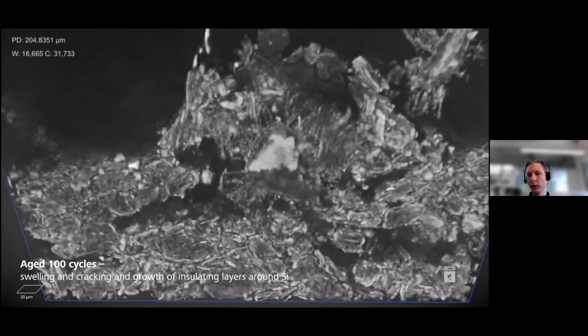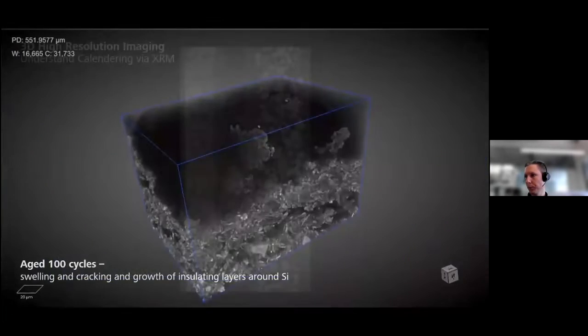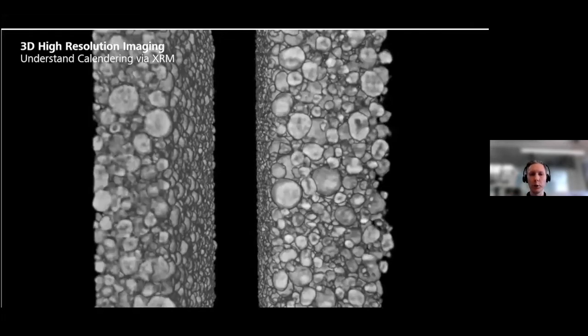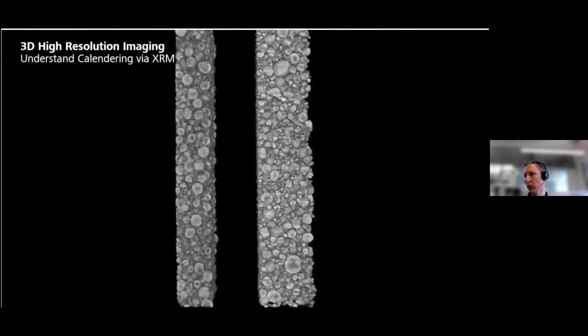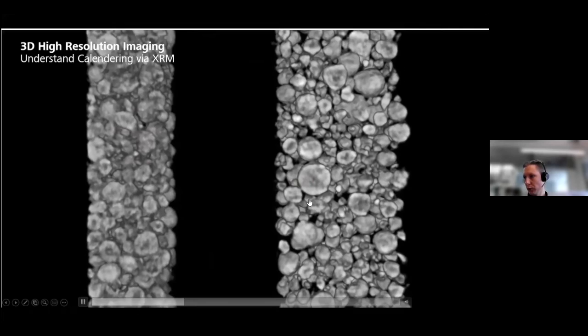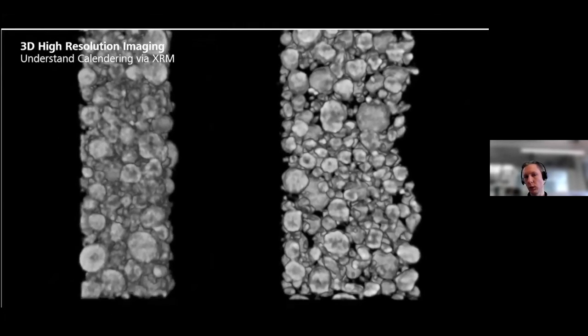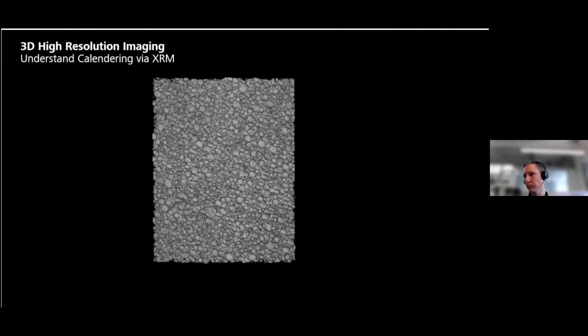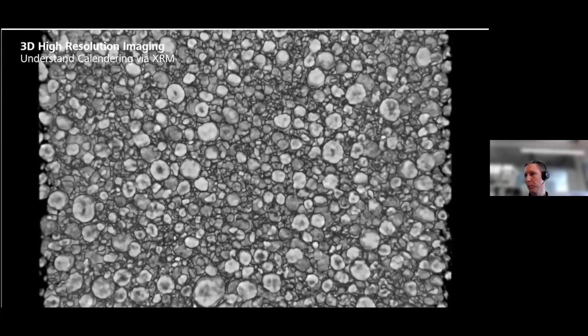You cannot only take a detailed look at the materials, but also use the X-ray microscope for optimizing your process parameters. Here we can see two samples produced with two different calendaring pressures. The density of the particles in the electrodes is of great importance. Using the microscopy, you can look at the single particles and see if they're not efficiently packed or too closely packed, or if there are cracks in the particles. So you can use it for both material research and optimizing the process at the very base level — important for cell performance after production and for safety reasons.